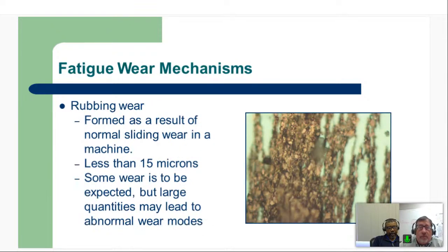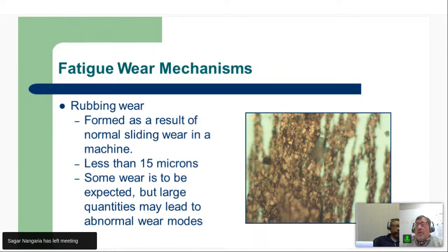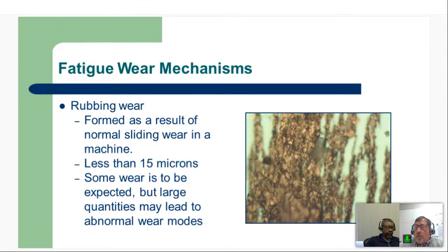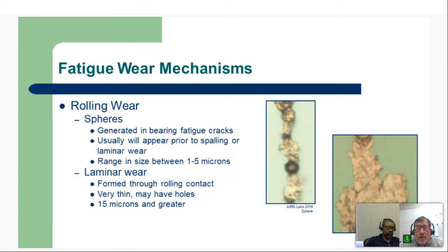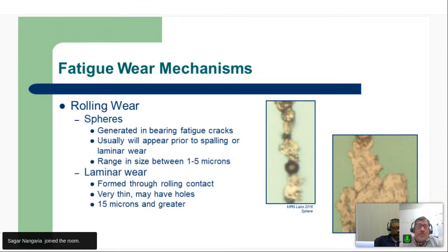That's correct. And then you've got fatigue wear. They might be normal rubbing wear, but like Ray says, depending on application, some wear is expected. But large quantities or large sizes are the things that trigger us to say, hey, something has changed here, and this is abnormal, and it needs to be addressed. Here are some fatigue platelets or laminar wear particles, like you see here on the right. And then we've got a smaller sphere here on the left that looks like a donut shape or a tire shape. The spheres get generated in the bearing fatigue cracks.